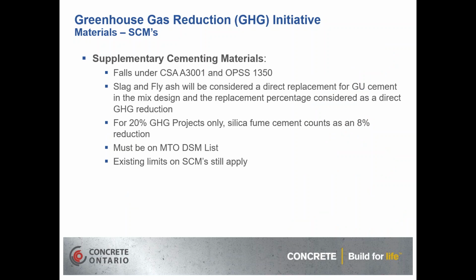Now, the supplementary cementing materials, again, they fall under CSA A3001, the cement standard, and OPSS 1350. Slag and fly ash will be considered a direct replacement for the GU cement in the mix design, and the replacement percentage considered as a direct greenhouse gas reduction. So if you have a concrete mix and you're running 20% slag replacement, then you're getting a 20% greenhouse gas reduction in that. And this is basically simplified math just to keep things simple for the accounting. So this is how they are crediting those numbers.